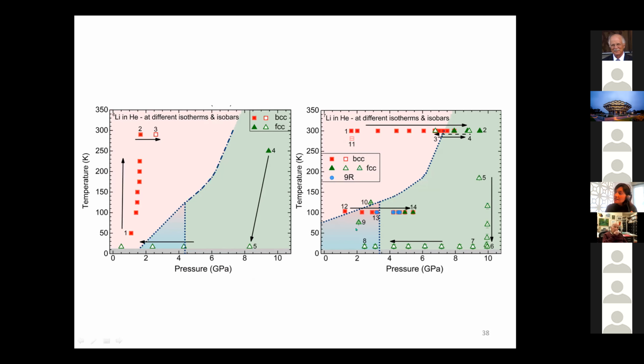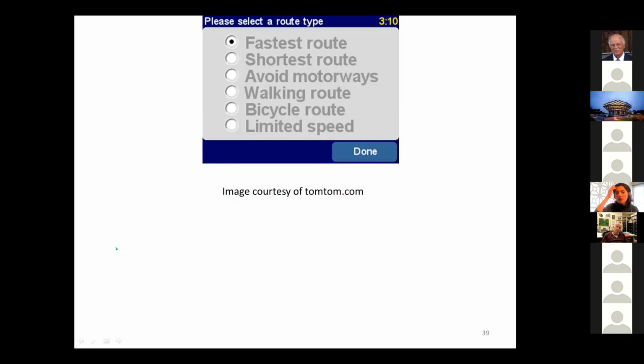So we basically synthesized, even at zero pressure, this FCC, which we believe is the ground state of lithium. The physics of it is that, as you look at GPS, it is not always the shortest route that is the ground state or lowest energy state, where you save the maximum amount of gas and get to the destination fastest. And this is what we have to be very careful about every time we do these high pressure experiments: the fastest route is not necessarily the ground state. A lot of times these kinetic effects take over and take you to different metastable phases.